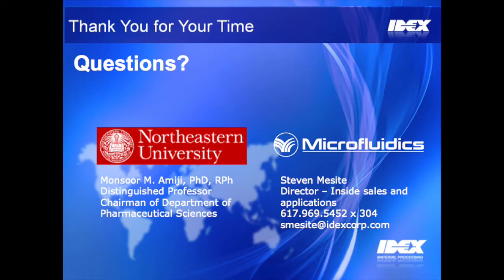So, good question again. There are several ways to characterize stability of nanoemulsion. I mentioned a couple in the discussion related to the DALDA peptide. So the most common, if you're just testing stability in vitro, is size of the droplet and changes in size of the droplet, zeta potential values over time, which is a very easy thing to do. You just take a small volume at different time points under different conditions of storage, and then measure the size and chart changes over time. And ideally, you shouldn't see more than a very small change, daily variation in the size and charge.